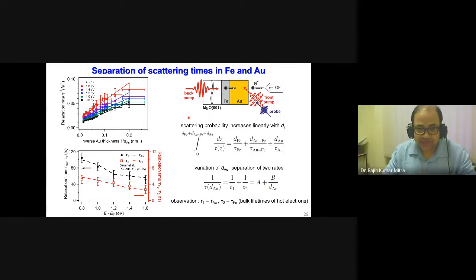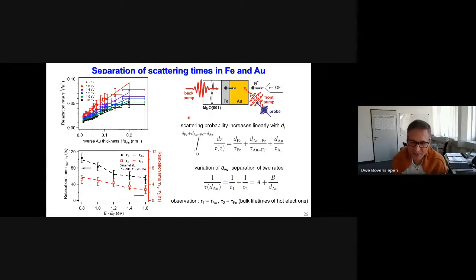Regarding this equation, I don't find any specific metal character in it. It only depends on D, the thickness of this interface, and no property of the metal comes into this equation. So is it universal in that sense? Very good question. I would rather phrase it this way: for metals, it works very well. If you consider metal-semiconductor interfaces, then band bending becomes important, and you could easily end up with potential barriers that you would have to overcome. So the whole potential is less trivial than in a metal-metal heterostructure. Nevertheless, it would be very interesting, and this is certainly something that we want to exploit further.